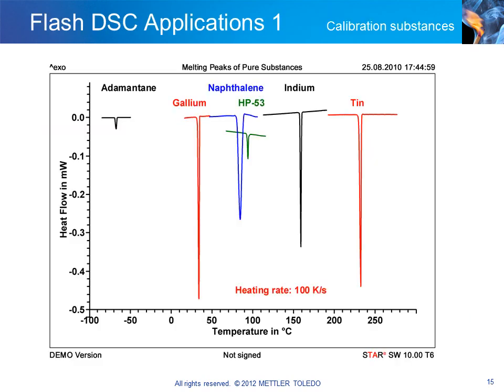Just as in conventional DSC, the melting point transitions of pure substances can be used to check temperature accuracy. The slide displays the corresponding curves at the melting points. The heating rate was 100 degrees per second. Besides the melting peaks of the metals gallium, indium, and tin, the solid-solid transition of adamantane at minus 65 degrees Celsius is also shown. This transition is suitable for checking the temperature accuracy below room temperature. Also shown are naphthalene and HP53. Both substances can easily be removed from the sensor.